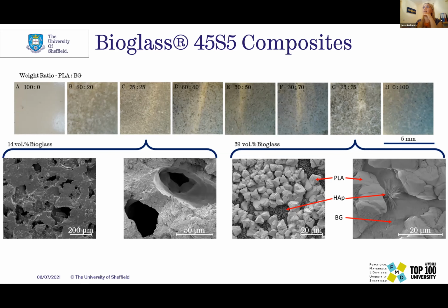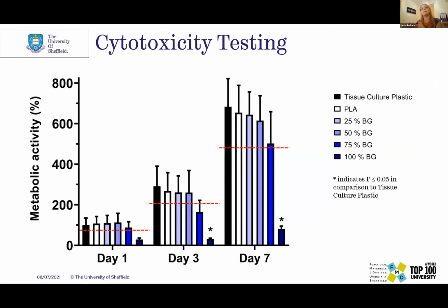The next thing that we looked at was whether this is cytotoxic. Is making these components via cold sintering making them more cytotoxic than conventional samples? So we compared all the different bioglass polymer composites with TCP and just the PLA after a 7-day dwell in media, which allowed initial alkali ions to dissolve into the solvent. We did that because we were working in a closed system, so we didn't overwhelm the cells that we then used.